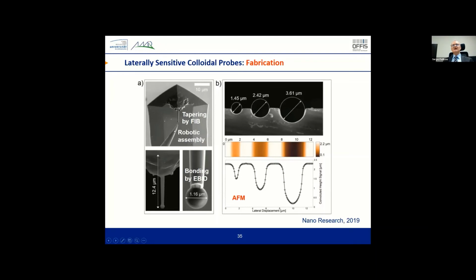Yeah, and we use a tungsten needle and robotic assembly to put the probe on the top of the column. And then afterwards, we use nanobonding by electron beam induced deposition. It's like gluing at nanoscale, so the only option for implementing bonding at nanoscale. And this is a validation of the approach.